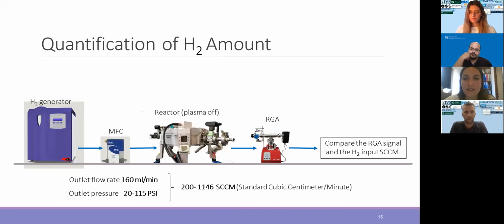But the next task was to quantify how much H2 we produce from decomposing water. We tried many, many methods, but none of them gave us any reasonable results based on what we see in the OES and in the RGA. So we figured out that the best way to quantify how much hydrogen we have would be to actually perform a calibration curve with real amounts of hydrogen, and then put our results in it to see where it falls.